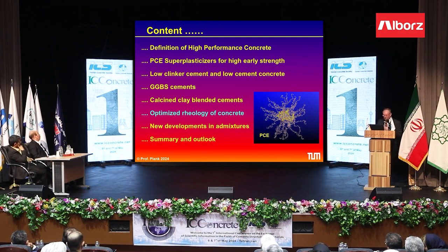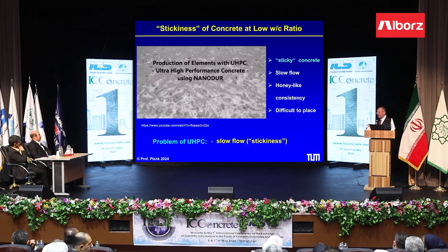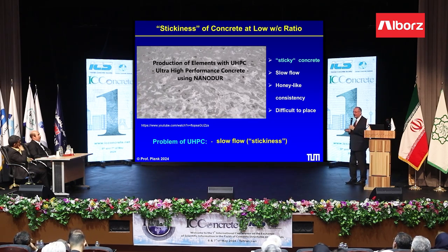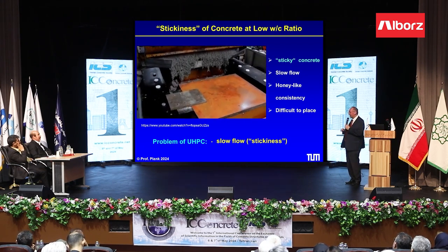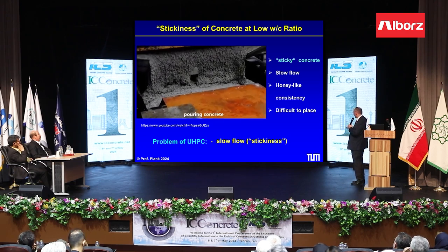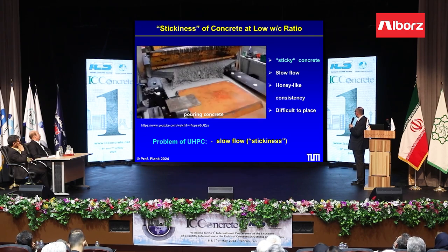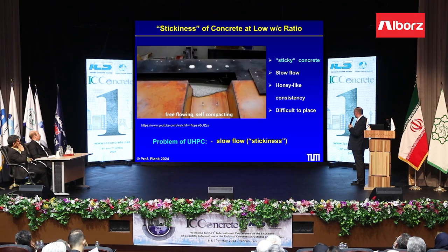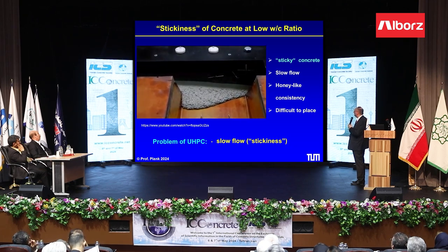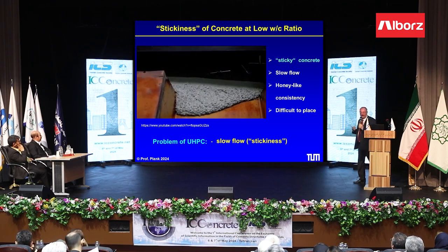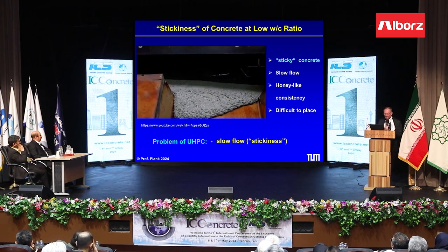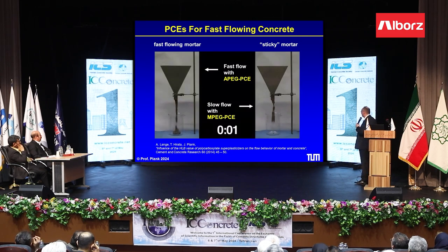Now, let's come to optimized rheology. A big topic in Germany is the stickiness of concrete. And as we go to lower and lower water to cement ratios, this problem, of course, becomes very severe. Here I show a concrete which was formulated with a water to cement ratio of 0.28, and it flows very nice, but very slow. It's sticky like honey, and of course on the job site you don't like this. And we tested different PCEs, like allyl ether PCE gives a much higher flow speed than an MPEG PCE. So the type of PCE already has an influence whether you have more stickiness or less stickiness.